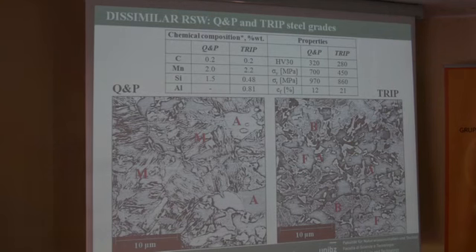Here in particular, you can see the chemical composition of the two examined steels. As you can see, these steels are mainly carbon manganese silicon steels. The main difference is due to the heat treatment that you saw before. And here you can see also the main mechanical properties of the steels: hardness, the yield strength, the ultimate tensile strength, and the elongation.